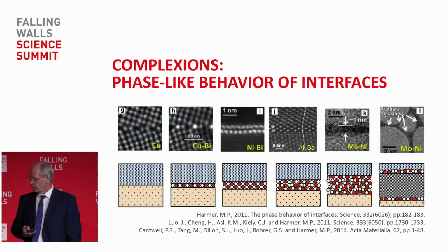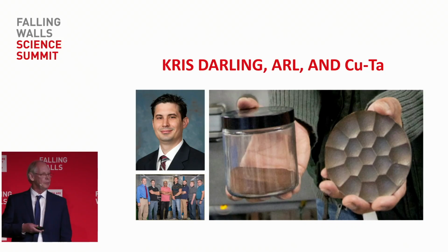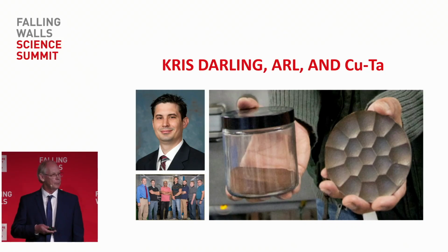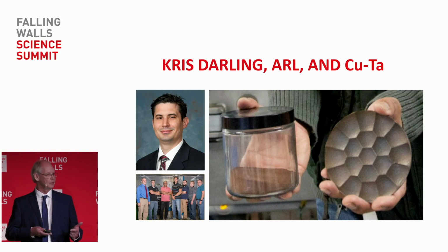So in the materials that we've developed, we've collaborated with Kris Darling's group at the Army Research Lab to make a superalloy from nanocrystalline copper. Copper is probably the last material you'd pick to think of making a superalloy out of. It's soft even at room temperature, and the nanocrystalline grains in pure copper are very unstable. They'll grow at room temperature.